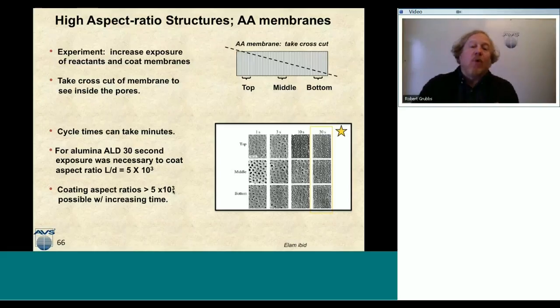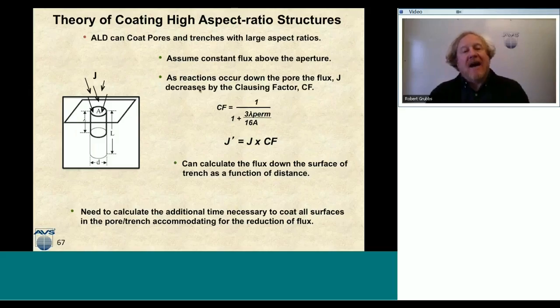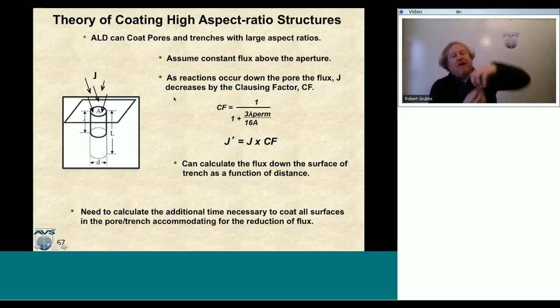So this has been quantified in more detail, and I probably won't go into this in too much detail, but here's the math behind coating a high aspect ratio structure, and this would be a dead-end pore. It wouldn't go all the way through. We have a certain amount of flux here on the surface that we know and love, that we can calculate from our previous learning, but as the reactions occur down the pore, the amount of flux that goes down a pore is decreased by this thing called the Clausing factor.